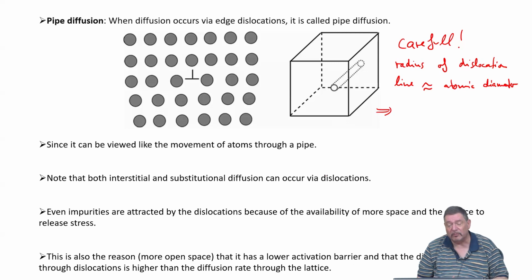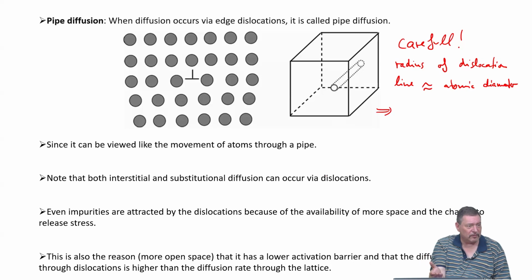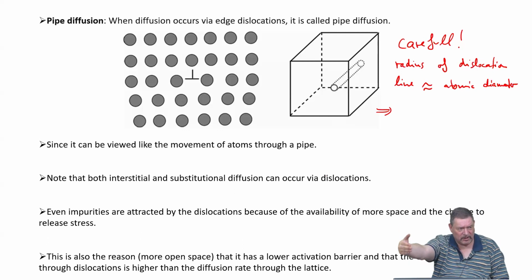This has an effect on the properties of the material, certainly, because you, for example, get preferential segregation of several of the atoms along dislocation pipes, and then you get these effects where you have dislocation motion prevented first by the segregating atoms, and only if a certain critical stress is overcome, then the dislocation can basically move away from the cloud of solute atoms, of impurity atoms, and then sometimes they move again to the new position of the dislocation.